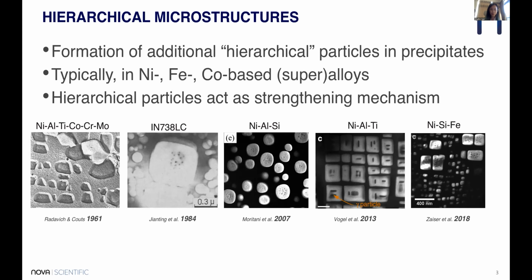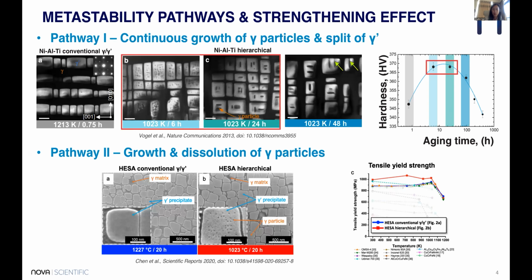Hierarchical microstructures change over time when exposed to high temperatures. And in general, we can observe two different pathways of metastability. Pathway 1 is continuous growth of a gamma particle and split of gamma prime. And pathway number 2 is growth and dissolution of gamma particles. This example of a nickel aluminum titanium alloy is following pathway 1. Spherical gamma particles emerge first in gamma prime precipitates and change their morphology into plates. The plates continue to grow and eventually split the gamma prime precipitates, which results in a loss of the strengthening effect. You can see this in the evolution of mechanical properties in the hardness curve on the right side here.